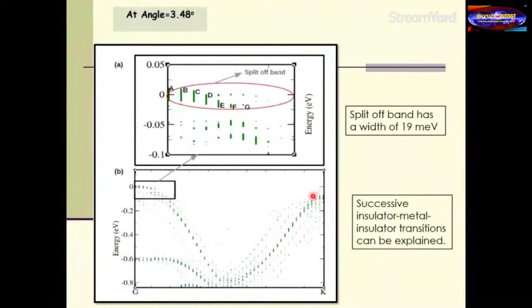We do have these dispersing bands, which we see over here. And when we zoom in, we see something very different, which is a localized state, and it's split off from the rest of the bands. It has a very small width associated, which is 19 meV, and these are the remaining bands. So what does this mean for us? This is my highest occupied band over here, and if I were to hold up this system, I go from a semiconductor, then I have this metallic behavior, and then again I have semiconducting behavior, and then again as it does this, I could have metallic, and so on and so forth.